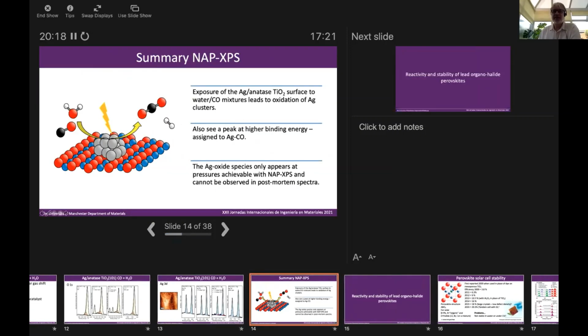So to summarize this short section on these photocatalysts, we've looked at the exposure of silver on anatase to water and carbon monoxide mixtures, and we found this led to oxidation of silver clusters. We also saw this higher binding energy peak, which we've assumed is due to silver carbonyl species, and that assignment comes mainly from other studies which have used FTIR to look at these kinds of catalyst systems. And as I said, the important thing is that the silver oxide species and the silver carbonyl species only appear at the pressures achievable with NAP-XPS, and we can't observe them in the post-mortem spectra. So we can't expose and then remove and go back and look at this again.